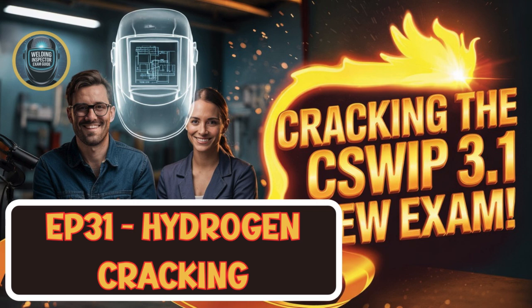What's number two? Number two is stress. You need significant tensile stress in the weld area, specifically stress that's greater than about half the material's yield strength. Half the yield strength. Yeah. And that stress comes from the welding process itself. Mostly, yes. Residual stress. It's just inherent from the heating and cooling, the expansion and contraction.